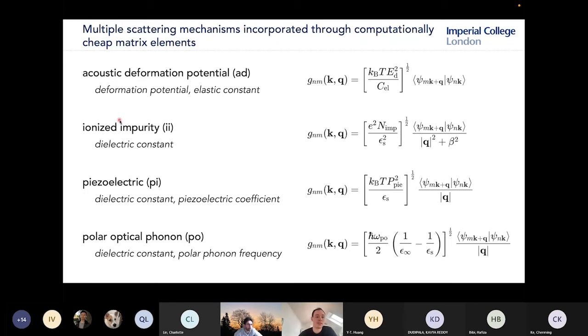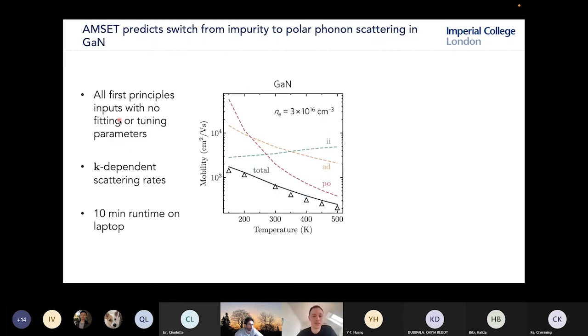So how well does AMSET do? This is just some results on gallium nitride. Here I'm showing temperature against mobility. The experimental values are these black triangles, and the AMSET result is this black line here. And I should just add that these experimental measurements are very high purity single crystal measurements, so we're minimizing the other sources of scattering which could limit our mobility further.